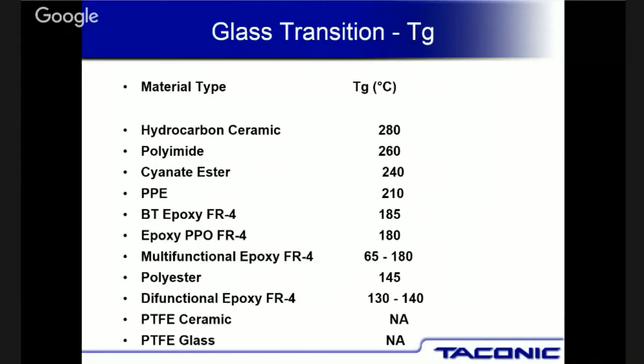Notice I put on the bottom 2 materials, Teflon materials. Typically, they don't melt. That's one thing about Teflon. Teflon gets softer as it gets very, very hot, but it doesn't actually melt and flow. So its CTE doesn't really change. Its actual glass transition temperature is something like 30 degrees centigrade, which doesn't make sense because that's room temperature or colder. But typically these materials can be used up to very, very high temperatures without worrying about the T sub G of the materials.